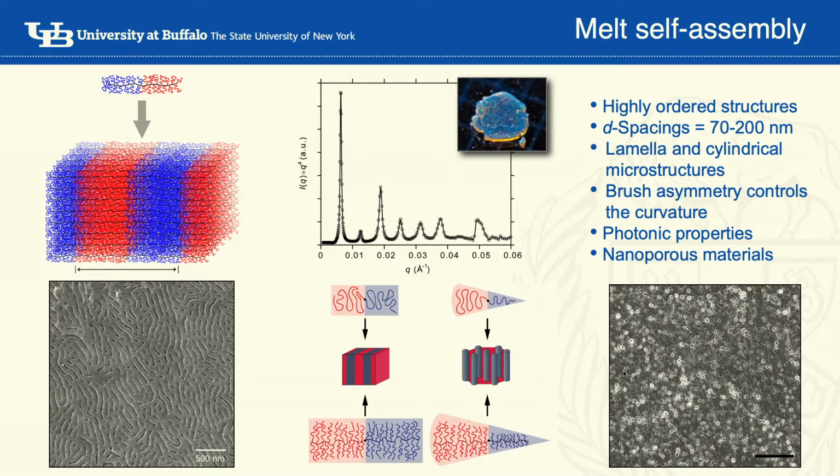If you look at spaghetti before cooking, you can pick out one spaghetti from the box and nothing else is stuck to it, right? If you cook spaghetti or noodles, and then you try to pick one noodle, it's very hard. Everything is entangled, right? That's the entanglement. So the flexible chains entangle, rigid chains don't entangle very much. And so this bottle brush, which is actually not good for mechanical properties, is good for self-assembly. So they're able to organize into these beautiful periodic structures.